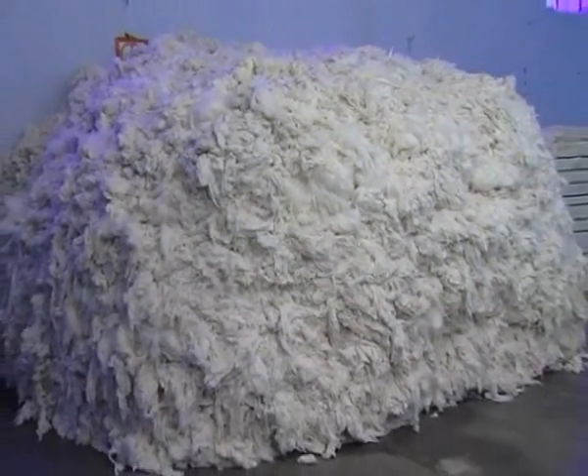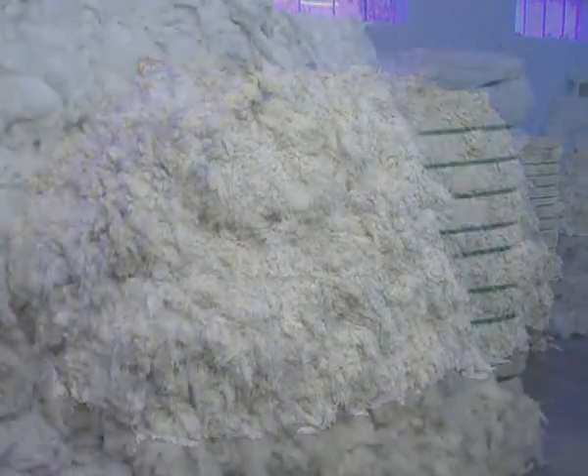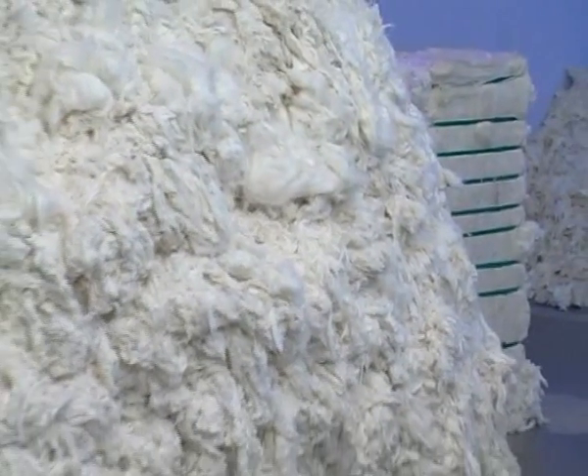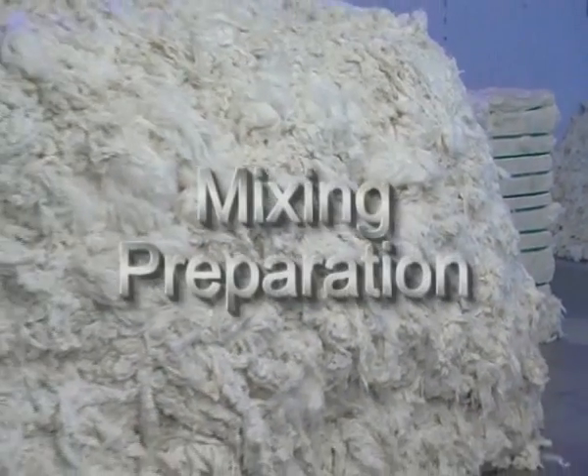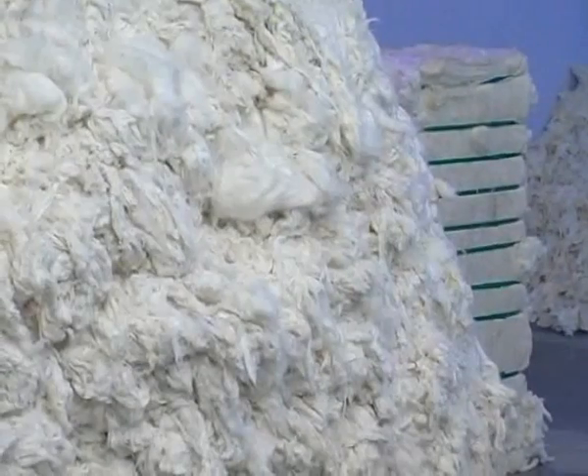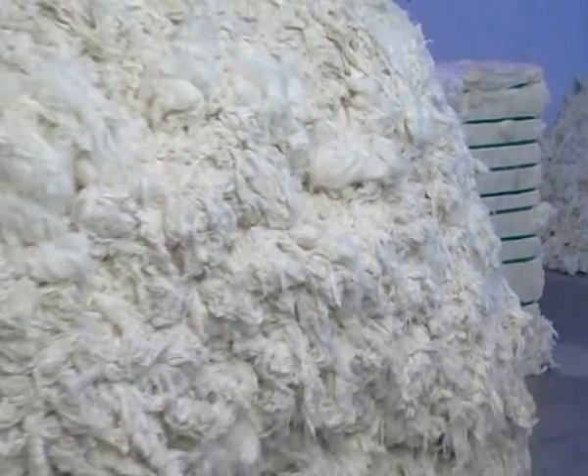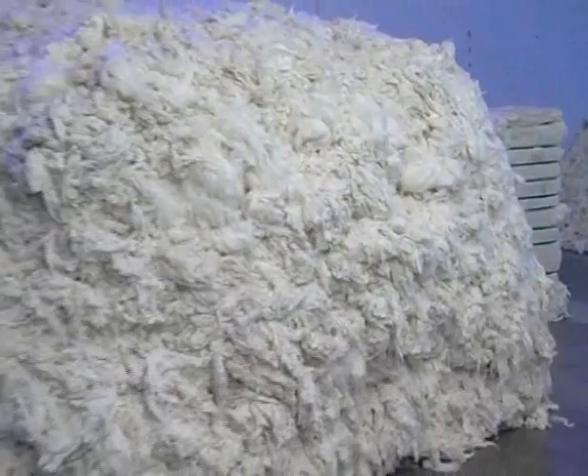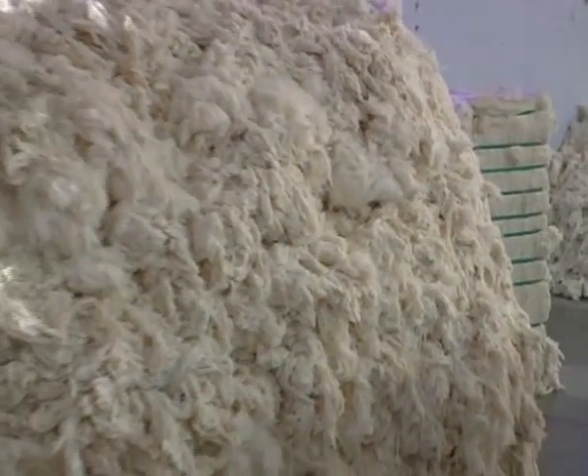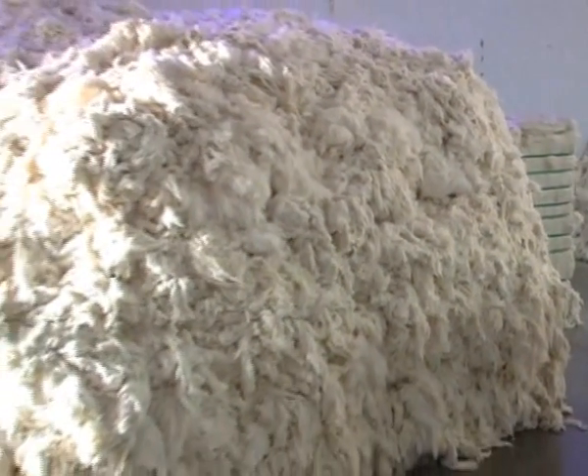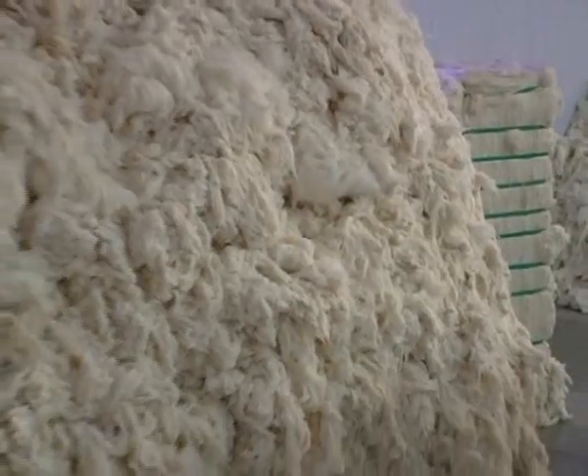Cotton arrives at the mill in large bales. These bales should be opened, cleaned and blended. Mixing preparation. Cotton fibers of different lots are stack mixed. About 10 to 12 hours of conditioning time is allowed for the fibers to have a suitable moisture regain. This ensures uniform blending of the fiber.